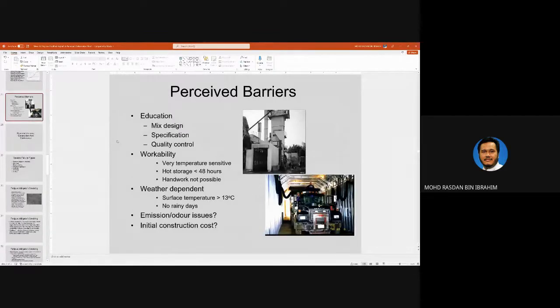Okay, the barriers. The education, which covers design, specification and quality control. Not many people are able to come up with the mix design for rubberized bitumen. The specification, the local specification: if you go through different specifications from different authorities, even in the US, in the same country, the variance is very high. One authority says maximum 8%, the other authority will say maximum 12%. The temperature that the specification instructs the contractor to mix at can also vary very significantly. So it's very difficult to really understand what's going on, because the quality of the mix is highly dependent on the type of rubber, the temperature of the mix, the duration of the mix, everything. So to get one uniform design is very difficult.